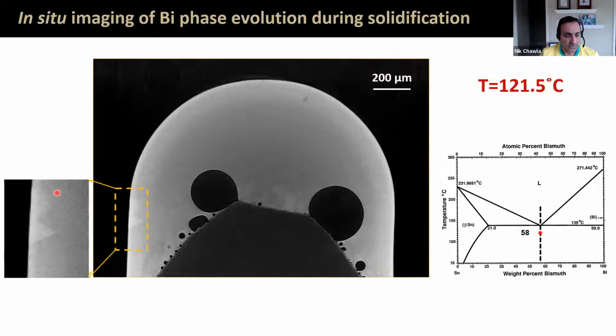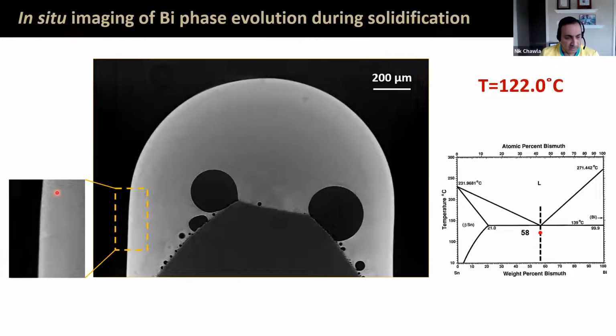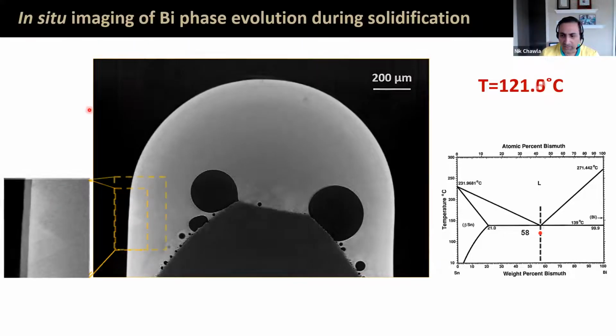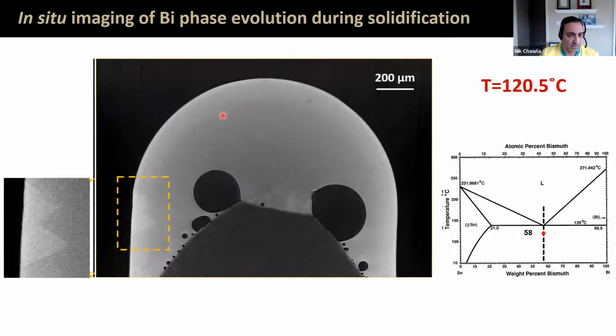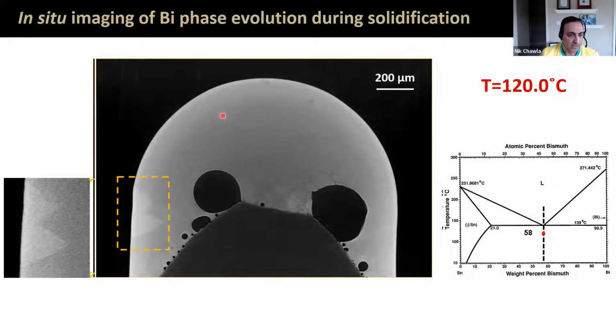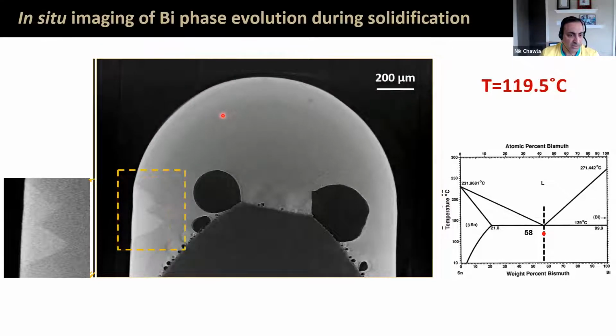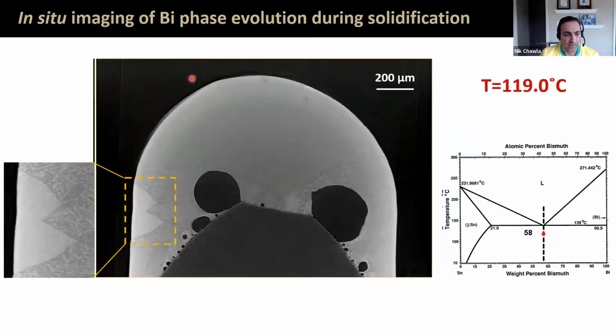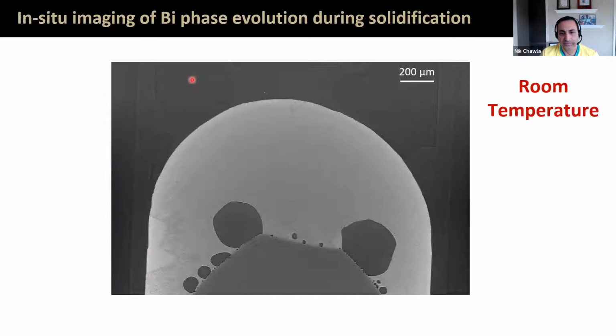So these actually show the pyramidal bismuth particles that are growing here on the surface. And as I increase the time, you can see the temperature here, and these particles are growing. And you can actually capture the change of those particles. Now the bismuth has solidified, and you start to see the formation of the tin bismuth eutectic microstructure, which is a divorced kind of microstructure.